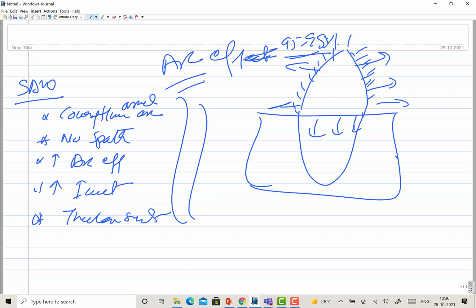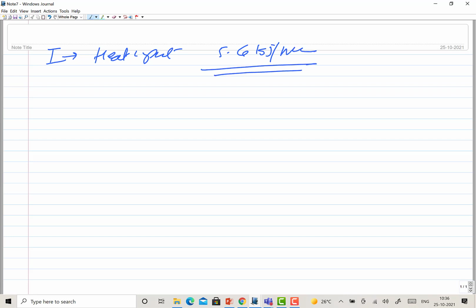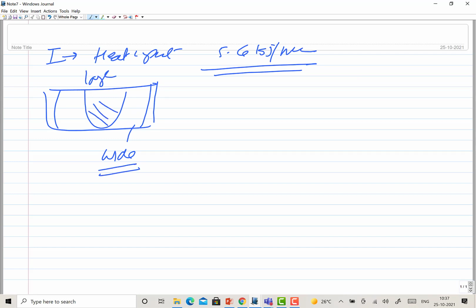So as far as the system is concerned, apart from these aspects, since the welding current used is very high, 1500 to 2000 ampere, the heat input in these processes is also high, like 5 or 6 kilojoule per mm is very common. Because of the high heat input, your weld size is very large, and the heat affected zone is very wide. So wide heat affected zone and large weld size, these are the side effects of SAW. When the heat input is more, heat input goes inversely proportional to the cooling rate encountered by the weld metal or the heat affected zone.